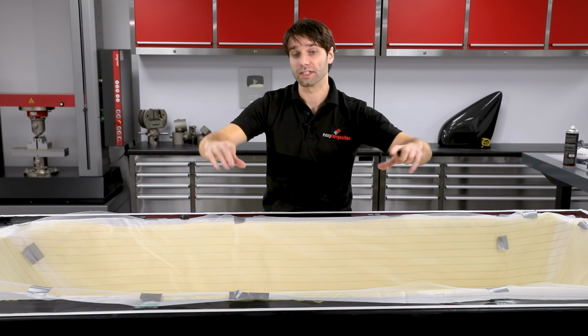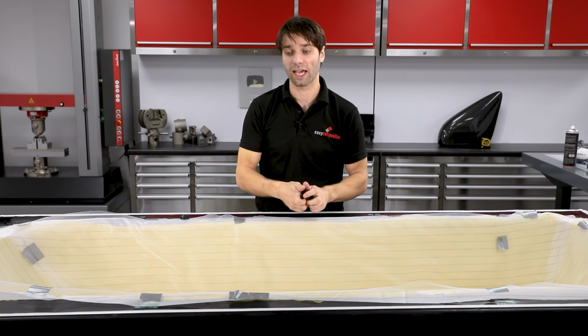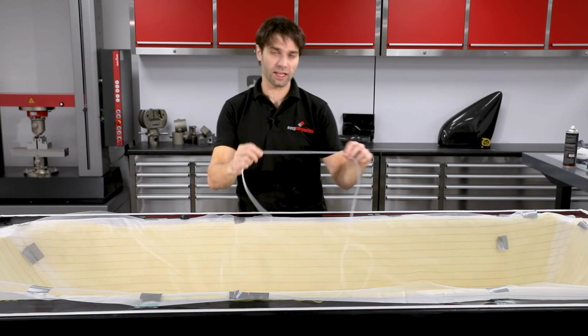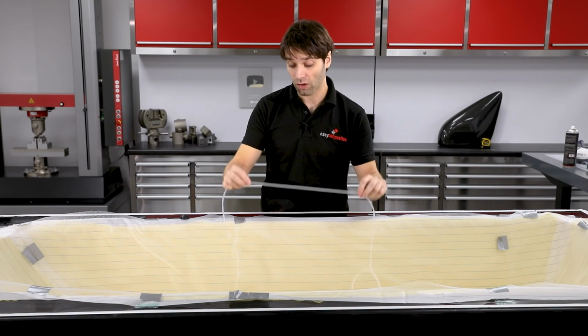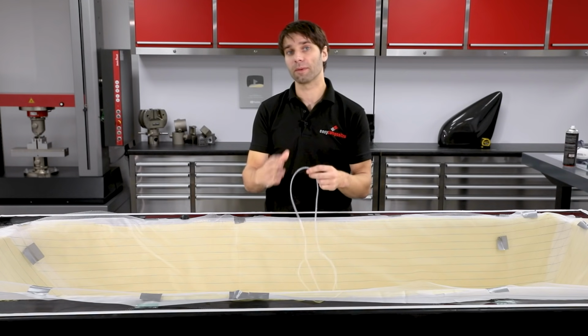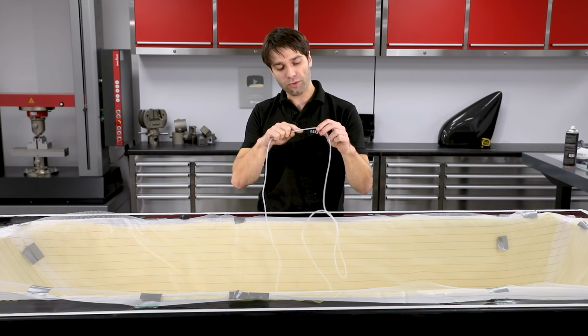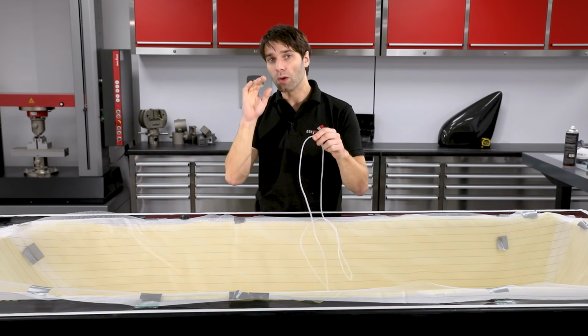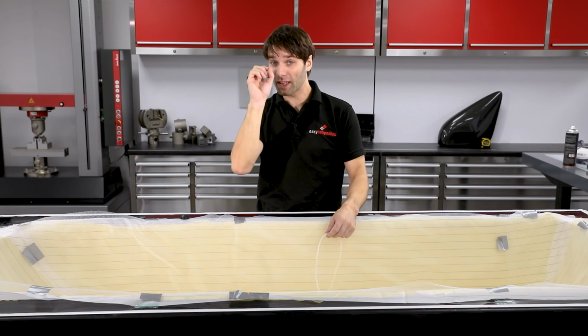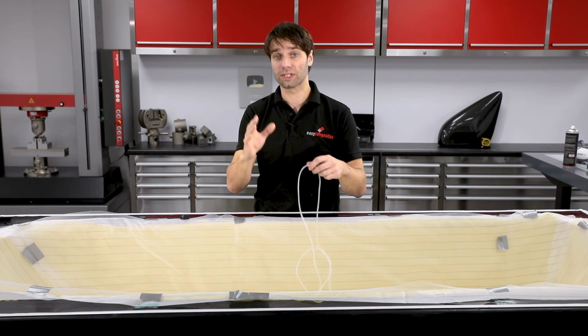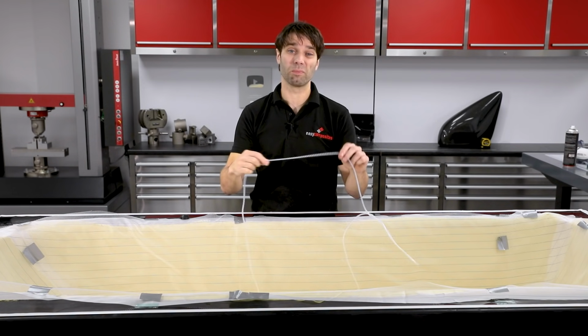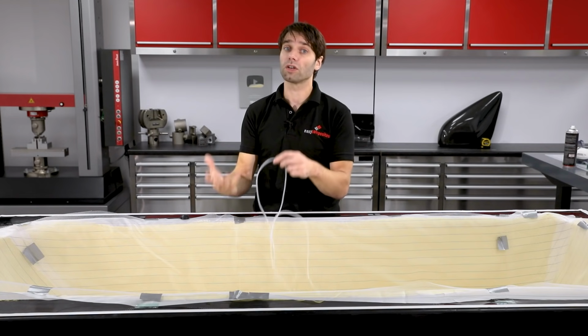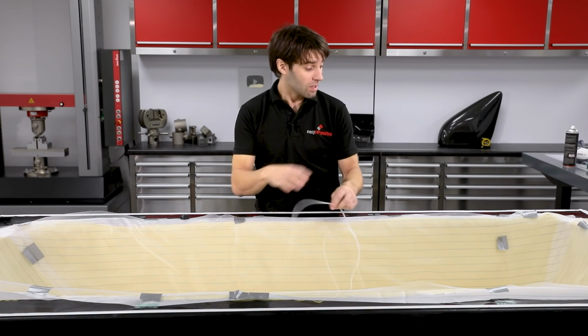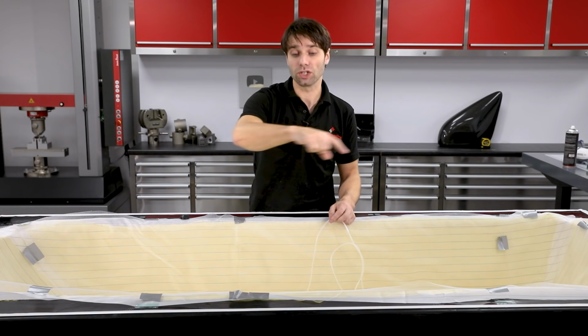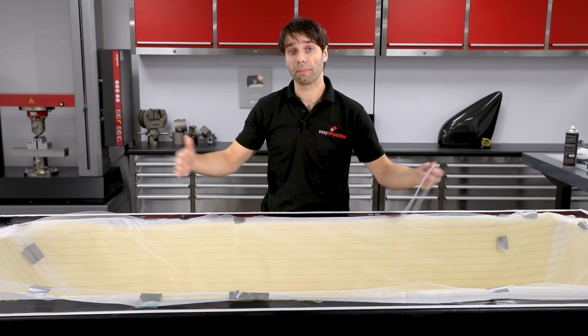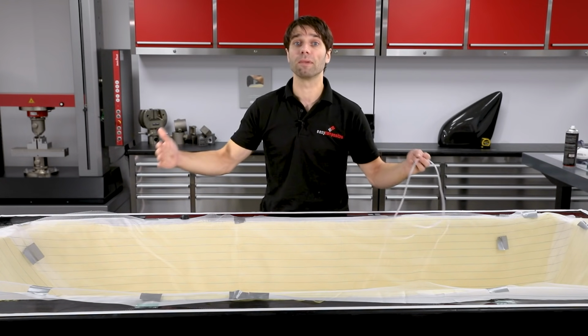You know, in the case of a Y shape, for instance, you could have 2 vacuum ports in 2 different locations. One thing that is worth noting if you need to run the spiral on the surface of the part, on thin cosmetic laminates, predominantly talking about carbon fibre here, the bridging of the bag over the top of this spiral will slightly imprint on the carbon, and so you will get a slight visible line. Now if it's a very flat panel, you'll see it. So you'll see this slight reflection in the carbon, and that would be a cosmetic imperfection. So wherever possible on cosmetic carbon parts, keep the spiral off the edge of the part, which is why for most things you're generally running in this U-shaped format, and you can go quite comfortably up to panels that are 1 metre, or if you stretch the rules a little bit, maybe 1.5 meters wide.